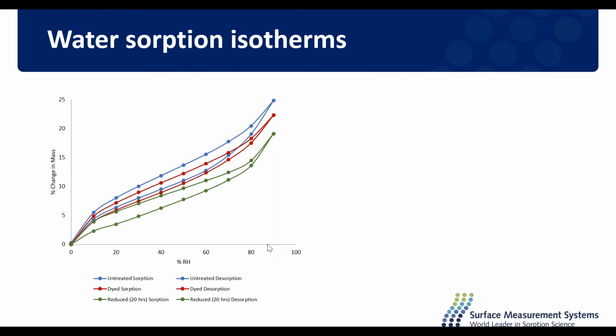And we were also quite happy with this data, as typically it's very hard to see significant differences in hair water sorption isotherms. And this is largely due to the hair's resilience. It takes a lot to damage hair. So we can see here with our reduced sample, we've really done some damaging experiments here.